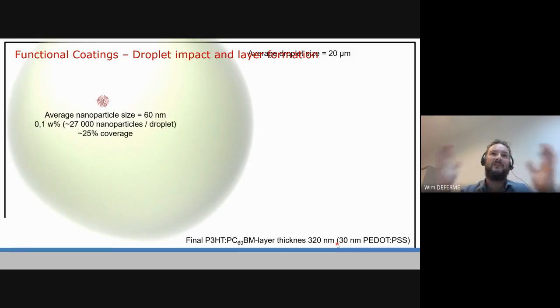If you compare that to nanoparticles having a size of 60 nanometers, and you put 0.1 weight percent of these nanoparticles, you have 27,000 nanoparticles per droplet. If you calculate that, based on specific properties of the ultrasonic spray coater, of course, you have, for example, a coverage of 25%. So if you then move over it four times, in principle, you think you have a coverage of 100%. Having a nanoparticle of 60 nanometers gives you this layer thickness around 300 nanometers.